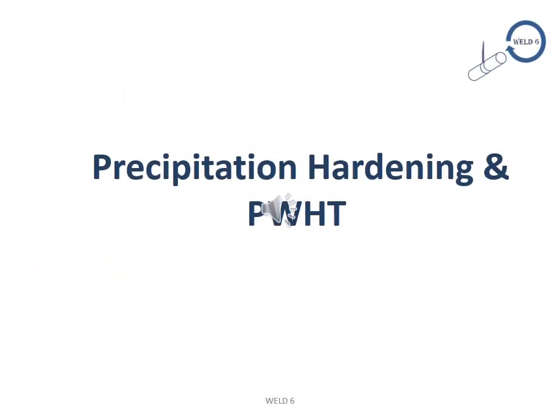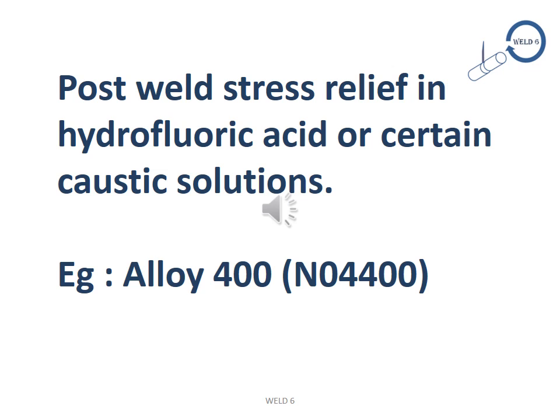Post-weld heat treatment may be required for precipitation hardening, also known as age hardening, in specific alloys. Post-weld stress relief may be necessary to avoid stress corrosion cracking in applications involving hydrofluoric acid vapor or caustic solutions. For example, nickel copper alloy 400, UNS number N04400, immersed in hydrofluoric acid is not sensitive to stress corrosion cracking but becomes sensitive when exposed to aerated acid or the acid vapors.